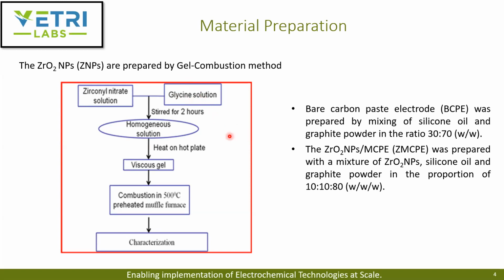Then they characterized it to confirm the presence of zirconia. And on the electrode side, how do they transform these zirconia oxide nanoparticles, ZNPs, into an electrode? They used a carbon paste electrode method. To know the influence of zirconia oxide nanoparticles, they made two electrodes. One is a bare carbon-based electrode, which they prepared by mixing silicone oil with graphite powder in the ratio of 30:70 by weight. And for the zirconia oxide modified carbon paste electrode, they prepared it with a mixture of zirconia oxide nanoparticles with silicone oil and graphite powder in a ratio of 10 to 10 to 80.